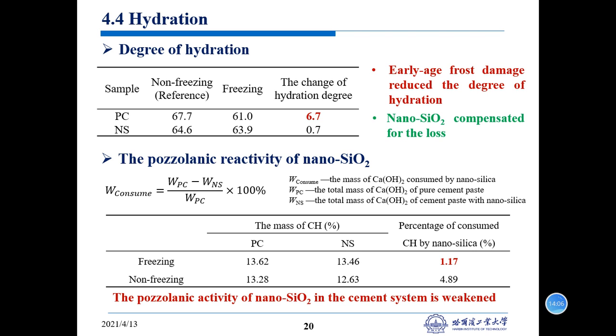The next one is the hydration. We can see the degree of hydration of the non-freezing and freezing samples in the chart of the hydration degree. We can see the early frost damage reduced the hydration degree, like this 6.7, and we can also see the nano-silica compensates for this loss. The change is just 0.7. We also use this formula to evaluate the pozzolanic reactivity of the nano-silica, and we can see the pozzolanic activity of nano-silica in the cement paste is weakened like this.